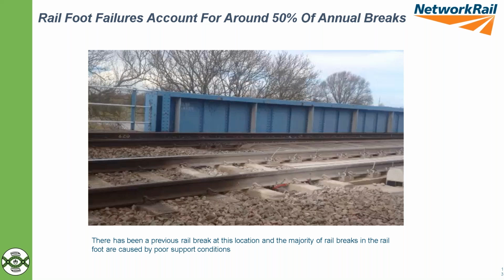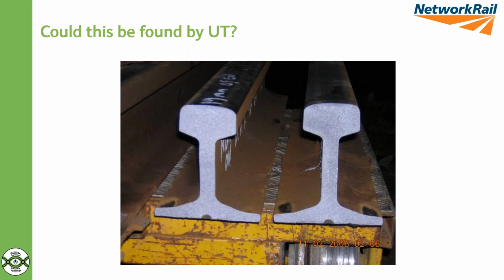But some of them, perhaps could we find by UT? A lot of work we do to try and do that. So for example here, you can see a small crack in the foot of the rail. This is actually quite a large defect compared with some of them that fail. But even the opportunity to find that, will it be in the middle of the web, directly under the web in the middle of the foot, where we might be able to get an ultrasonic signal to it?